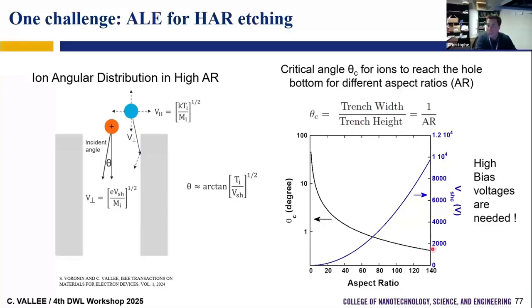compared to 90 degrees plus or minus 1 degree, to be able to have ions coming to the bottom of the structure when you have an aspect ratio of 140. So the only way to reduce it is to increase the sheath voltage. So it's to increase the bias voltage you apply.